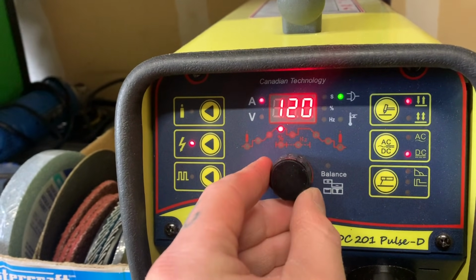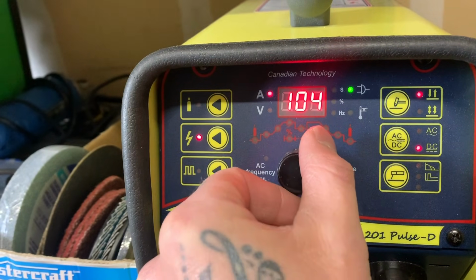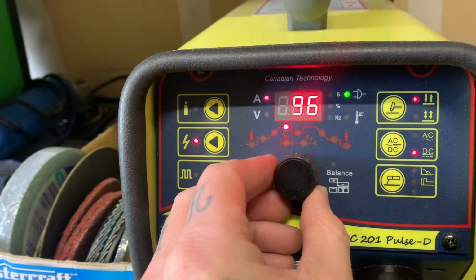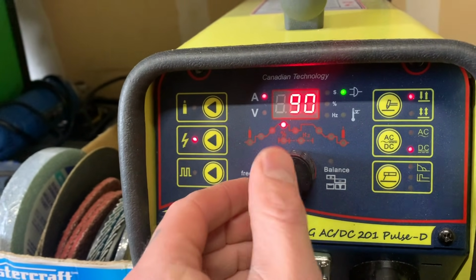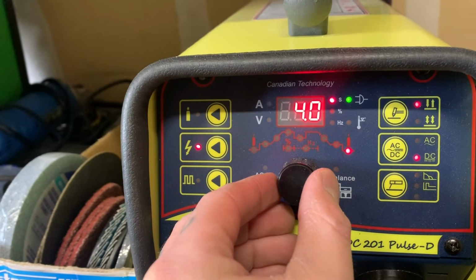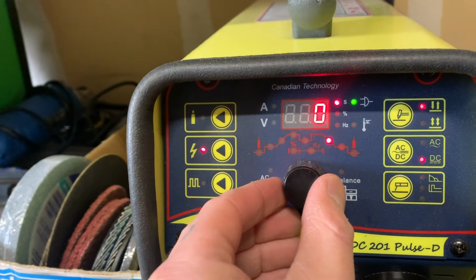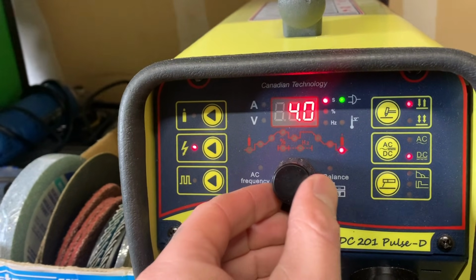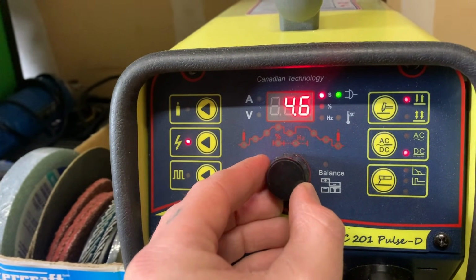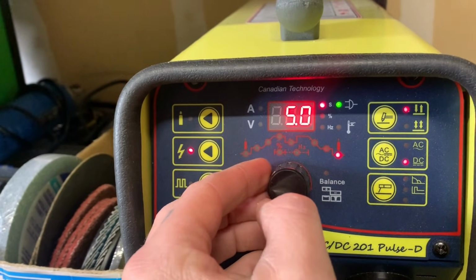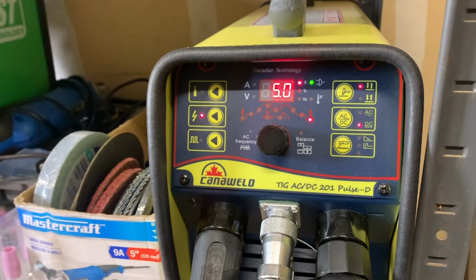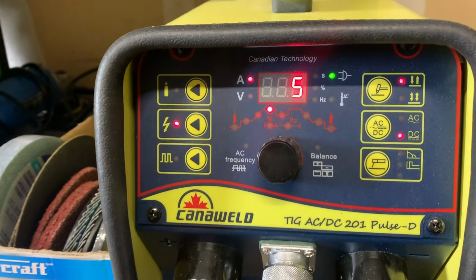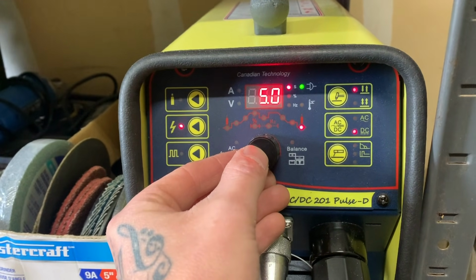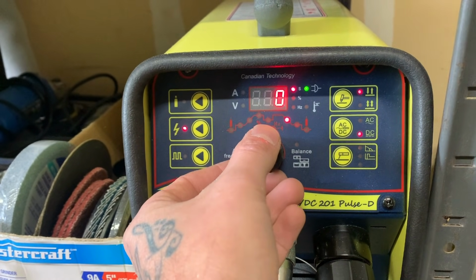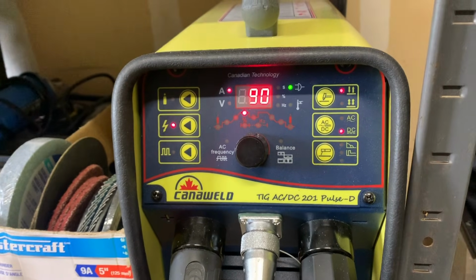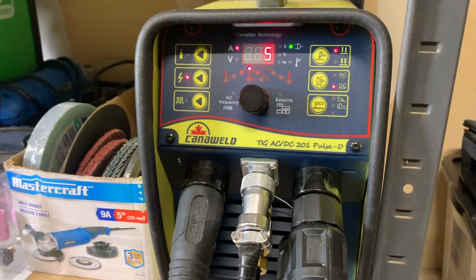I'm gonna turn this down. We're probably gonna run about, let's go with 90 amps. Again, we don't have upslope or downslope because we're using a foot pedal. But most importantly, we're gonna run a little bit extra on our post flow. So we're gonna run about 5 seconds of post flow. What this is going to do is that when I finish the weld, gas is going to continue to come out for 5 seconds, so that even though we're done welding, we're still going to have the gas coverage to keep our weld area nice and clean.